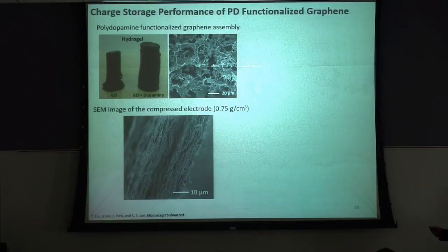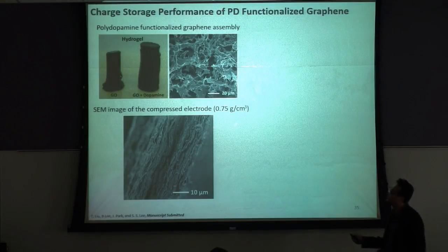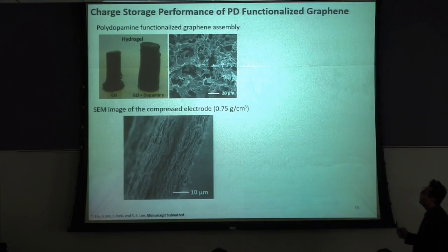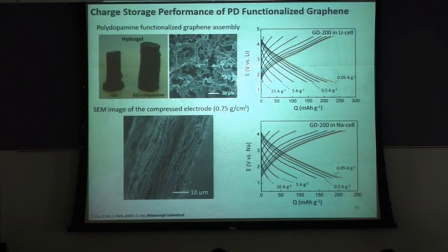So then as you can see, this electrode has pretty high porosity, right? So probably the density is pretty low. So we just mechanically press these electrodes, and we can get this kind of compact, highly packed structure electrodes. The density is now 0.75 gram per cc. So we measured capacity. Based on the total electrode mass, now the capacity has been increased, close to 250 milliampere hour per gram in lithium cell, also over 200 milliampere hour per gram in sodium cell. So we significantly increased the overall capacity based on the total mass of the electrodes by using this hydrothermal polymerization process of the polydopamine.